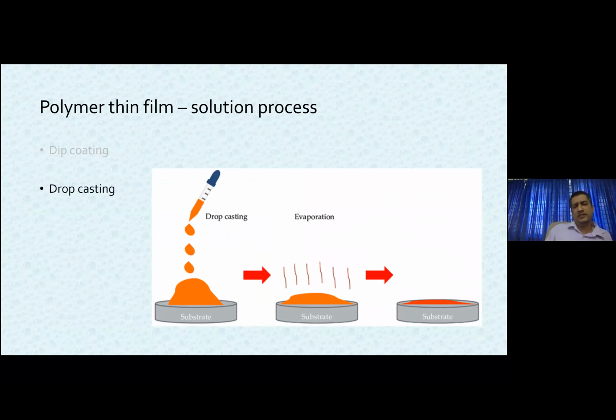Another even simpler approach is the drop casting approach. And in the last talk, we spent more time on understanding the coffee ring effect and other movements of particles due to the evaporation of the drop casted solution. So what happens in drop casting is that if you are not able to maintain the viscosity of the solution evenly, there is a possibility to generate an uneven film. Either it can form a coffee ring effect while drying, or it can have both a coffee ring and also concentrated deposition at the center of the drop.